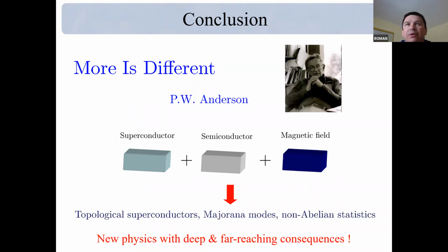However, if the hexagonal shape introduces a very strong perturbation, then this MJ quantum number is not a good quantum number. Therefore, in the absence of this quantum number, also the restrictions are absent, and one has to calculate a topological invariant, which is still valid for a given band structure. And what we find is that depending on the radius of the wire, we either have or do not have a topological region there. So it's a very detailed, specific question, but it's possible to have it if the rotational symmetry is broken strongly.